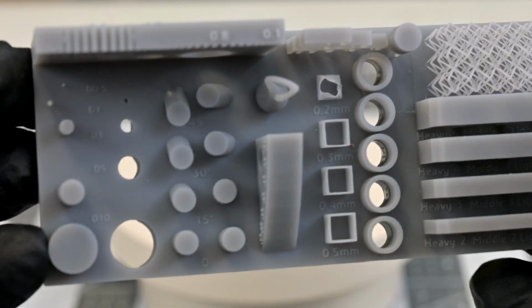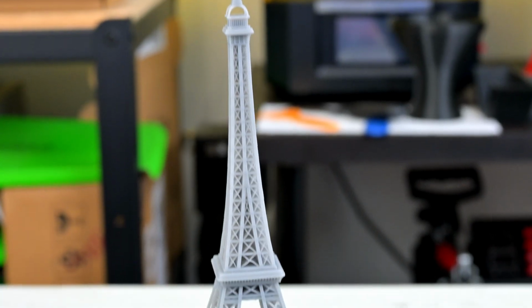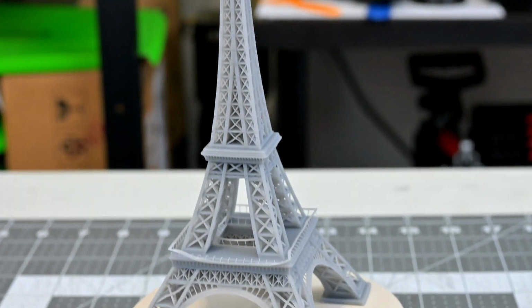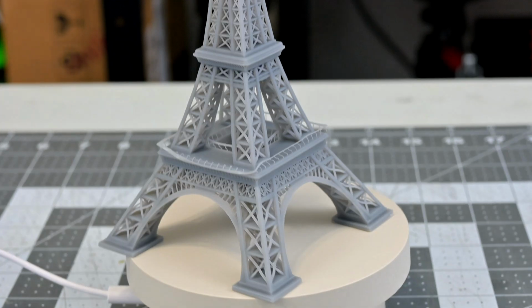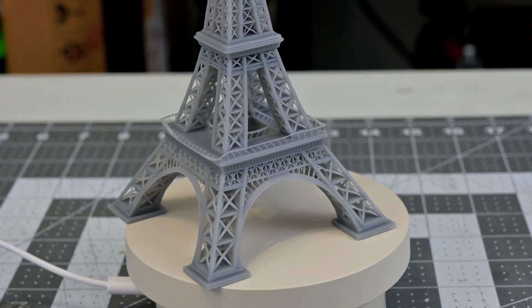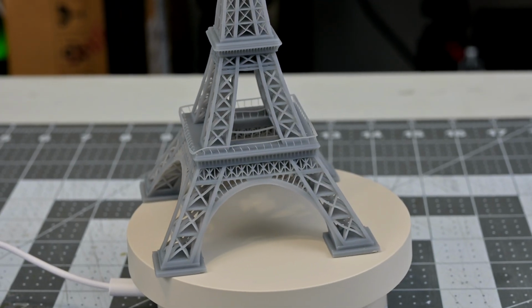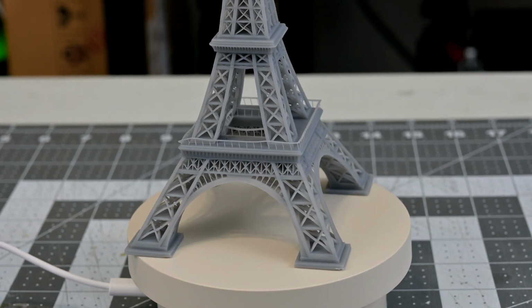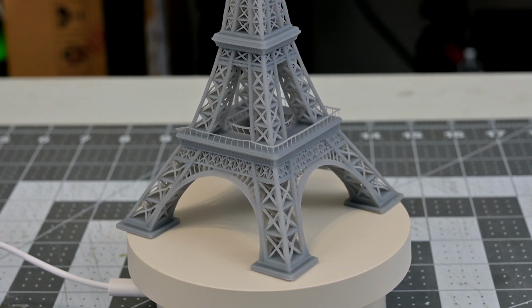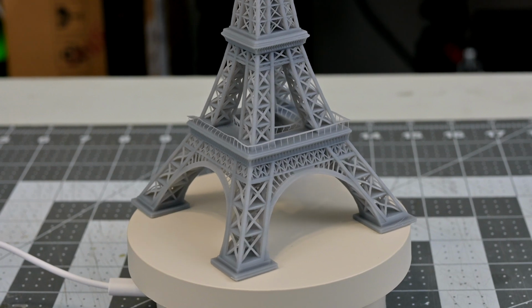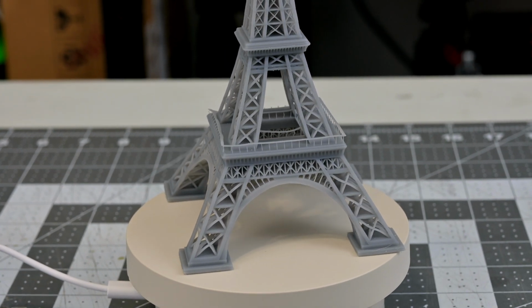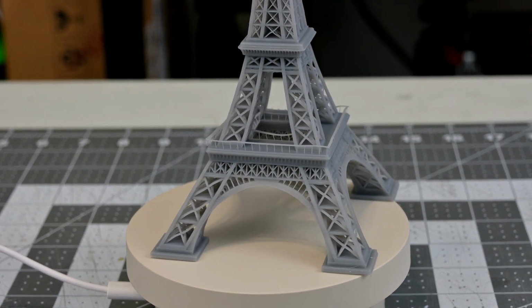I also love the Eiffel Tower as a stress test for resin printers. And the Creator Tough resin is interesting. I think the semi-flexibility caused an issue with the railing around the first floor. The railing and pillars printed, but I think that they buckled during the washing and curing stage. You can see similar effects with the thinnest of the lattice members, where they have a little bit of wave to them. The thick members had enough stiffness to remain straight, but the thinner ones were a little flexible.